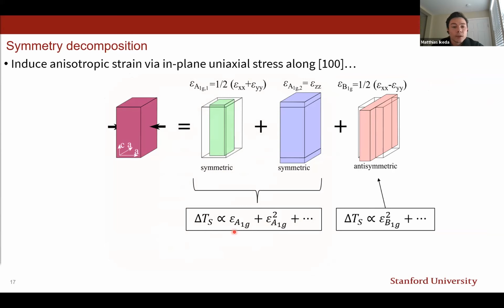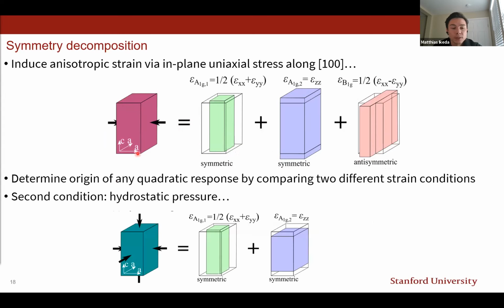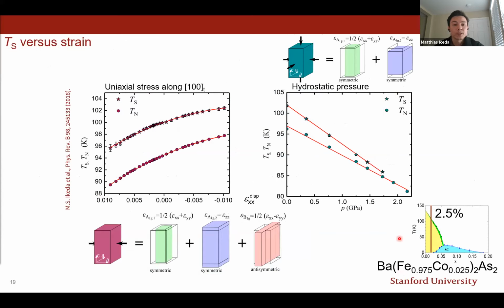So it is easy to imagine that from just one uniaxial stress experiment, it is impossible to disentangle the effect of symmetry conserving or symmetry breaking strains on the phase transition temperature. However, we can disentangle the effect of each of these strain components if we compare our uniaxial stress experiment to hydrostatic pressure experiments as well. And so this is what's shown again for 2.5% cobalt doped barium iron arsenide here on this slide.